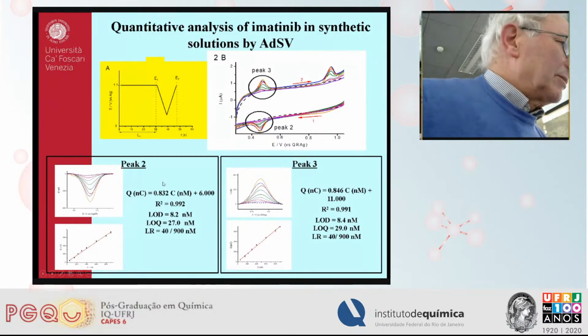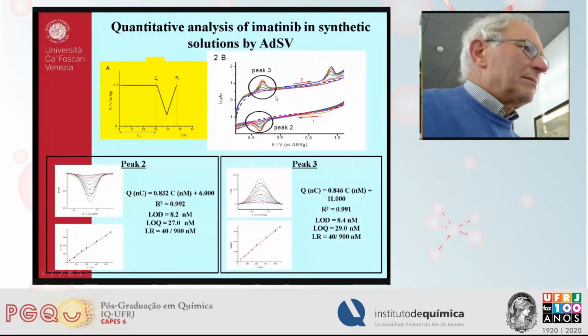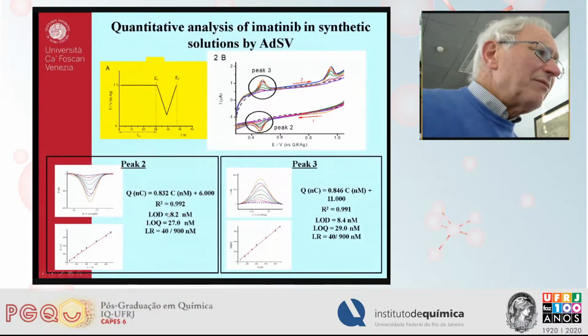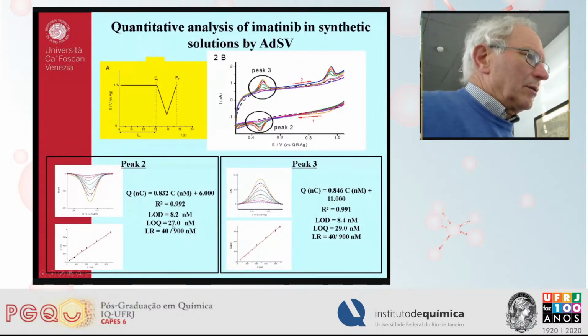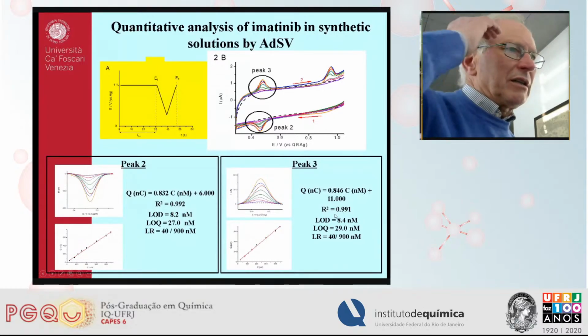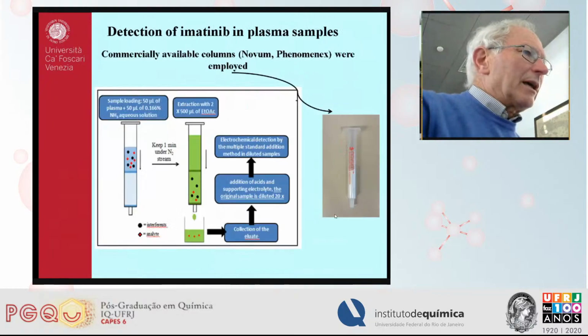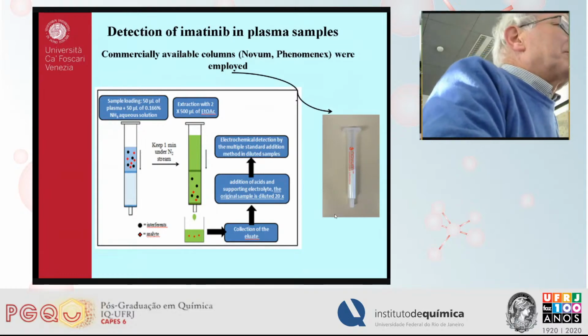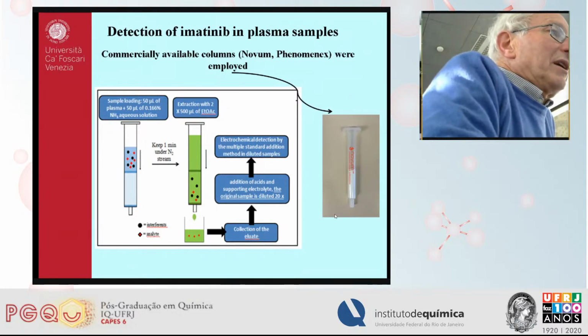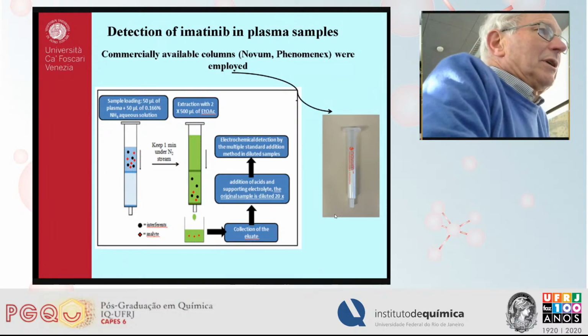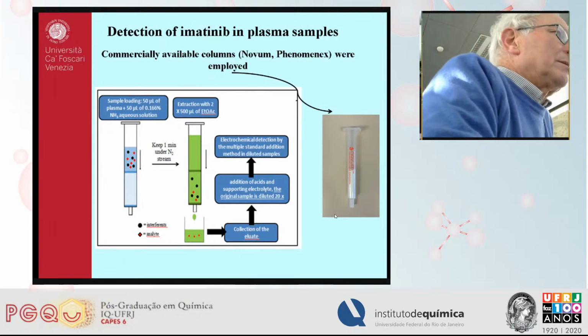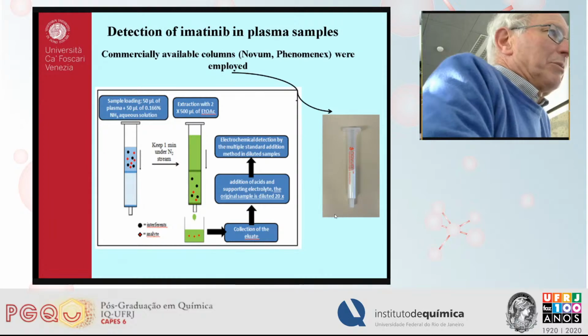These are the equations we obtained from the regression line, which provide a very low limit of detection, around 8.2 nanomolar, and limit of quantification of about 27 nanomolar. The linear range was between 40 and 900 nanomolar for peak 2, and similar characteristics were obtained for peak 3. Again, in this case, we have to deal with the interferences due to endogenous compounds, which cannot be eliminated directly from the plasma matrix unless one does some separation before the electrochemical measurement.